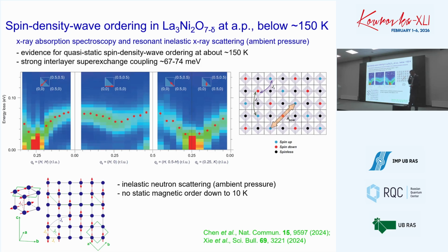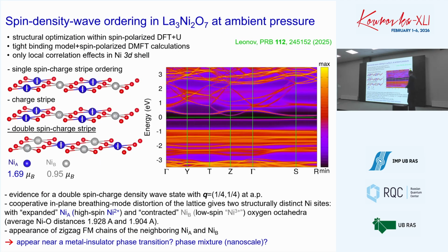Yeah, this is about spin density wave ordering. These are very recent results, one or two years ago. Two different techniques show relatively similar behavior, that there is some kind of tendency towards a combined spin charge density wave state in this material, and strong interlayer superexchange coupling, similar to what we discussed for infinite-layer nickelates.